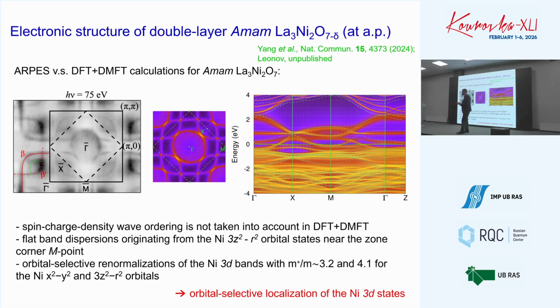This is what I still don't quite understand. There are some qualitative uncertainties for these materials, and the main issue is that only now people start to publish data about oxygen non-stoichiometry of their samples. It varies very dramatically, I mean, by 10%. And possibly these are oxygen deficient samples, which are metallic, which show some possible short-range correlations, I mean short-range density wave, which doesn't really renormalize the Fermi surface. The charge density wave should open a gap on the Fermi surface, or some Fermi surface sheet should disappear, at least one of them.